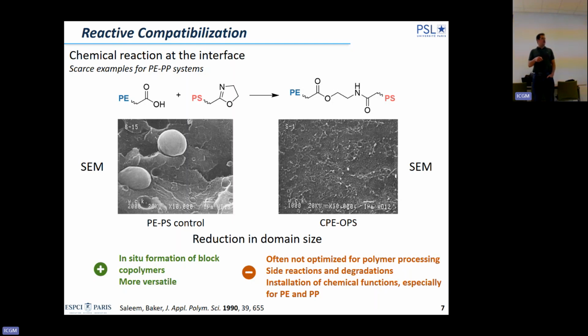And here you have an SEM image, and you see you can go from a big object to something which is much better dispersed. So this is an indication, one of the ways you can observe this, of the increase of the compatibility by the reduction of the domains of the dispersed phase, just a surfactant effect.